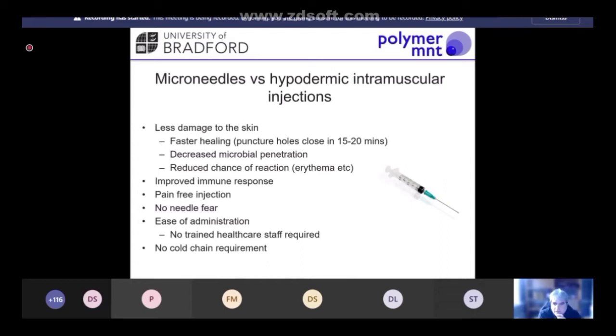Well, one of the main ones is by having lots of smaller needles instead of one big needle, we create lots of smaller holes which heal much more rapidly than hypodermic injections. So the puncture holes themselves will close to a point where they're almost undetectable in just 15 to 20 minutes. We're also penetrating less deeply through the skin as well. And there's less microbial penetration, so there's less chance of infection using these microneedle devices because we're making a smaller wound or a smaller set of wounds in the body. There's also a reduced chance of reaction as well because we're doing less damage to the local area. So generally, we're doing less harm to the skin, and we're seeing much faster recovery times.